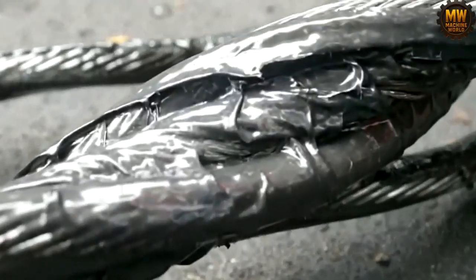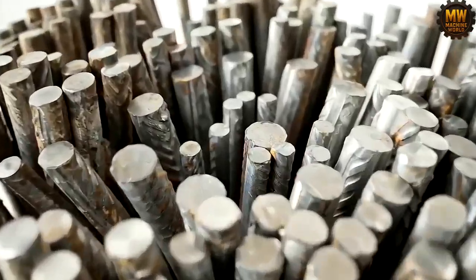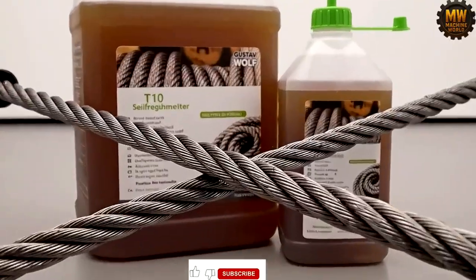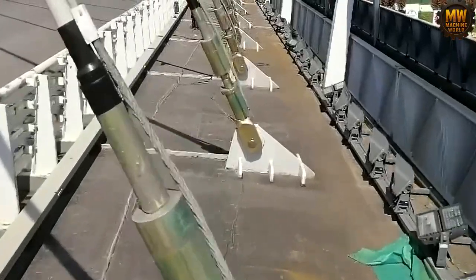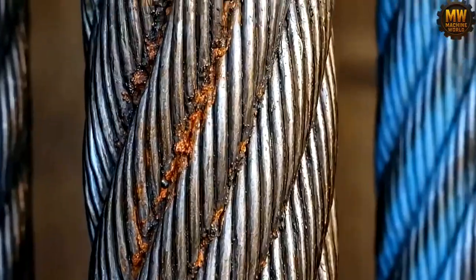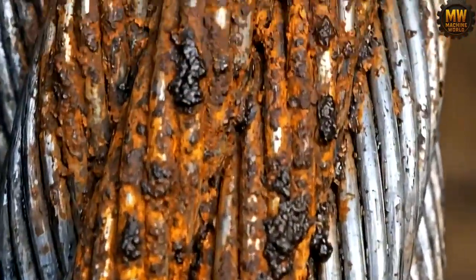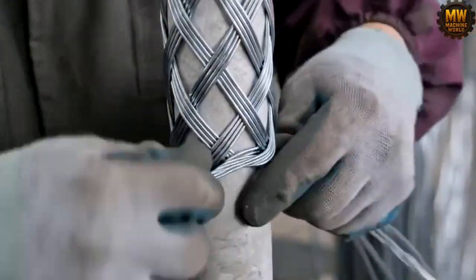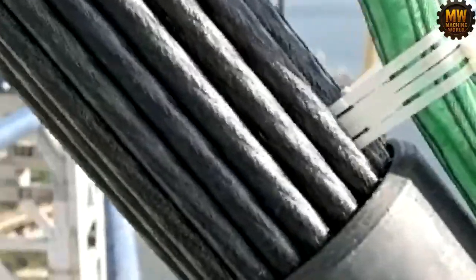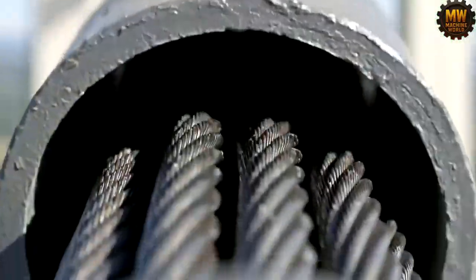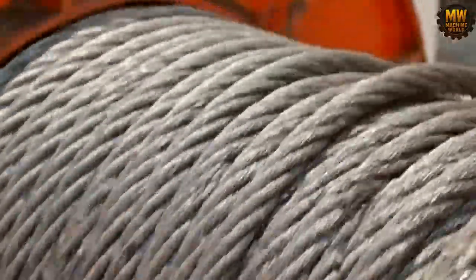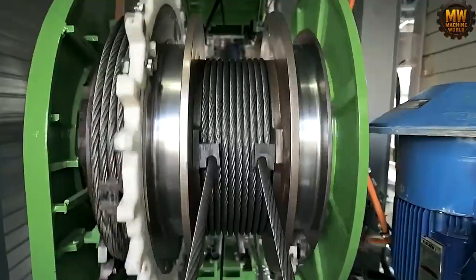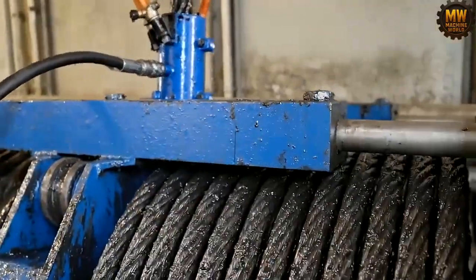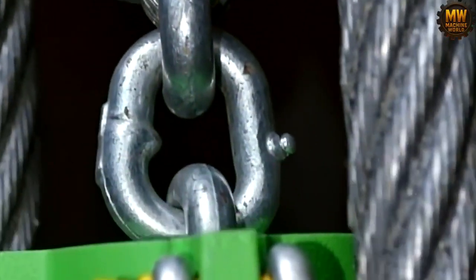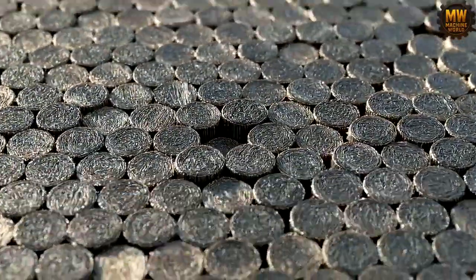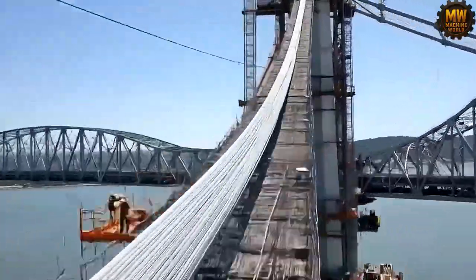But even a perfect computer assembly leaves microscopic voids. Without special treatment, these gaps will become an incubator for hidden corrosion. Condensation acts as the silent executioner of megastructures. The braided monolith passes through a high-pressure injector ring. Heat radiates from the massive steel nozzles. A viscous, gleaming wave of hot synthetic lubricant blasts into the cold metal matrix. The mechanical pressure forces the thick liquid deep into the core. It penetrates so thoroughly that it floods empty spaces thinner than a human hair.